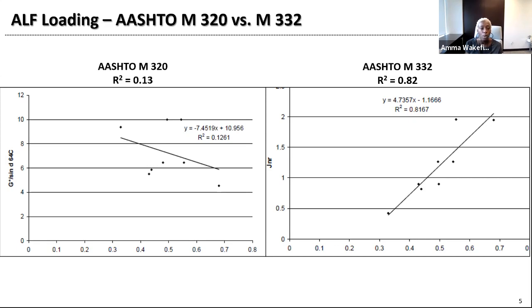Because it's important to show the data that supports this statement, here is where we're showing the comparison between the parameters that are used to characterize rutting. So in the MSCR specification, that parameter that's related to rutting at high temperature is called the non-recoverable creep compliance, or the Jnr. If you look at the graph, I'm going to explain what both of them are showing, but the parameter in the AASHTO M320 specification that characterizes rutting is the G* over sine delta. So these two parameters are both characterizing rutting, but in the two different specifications.